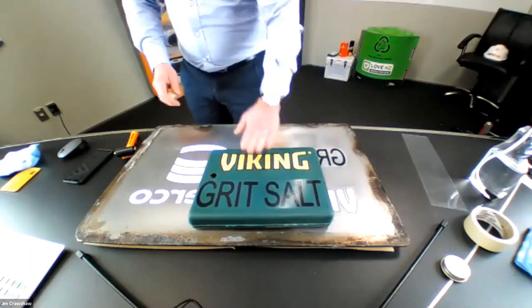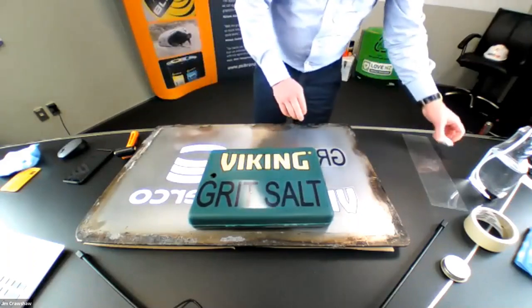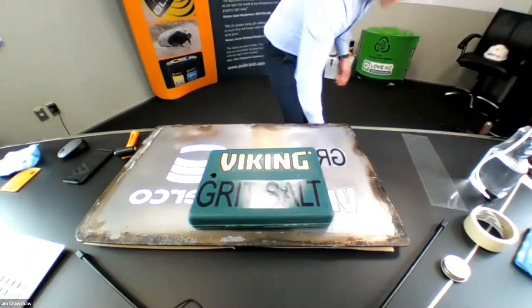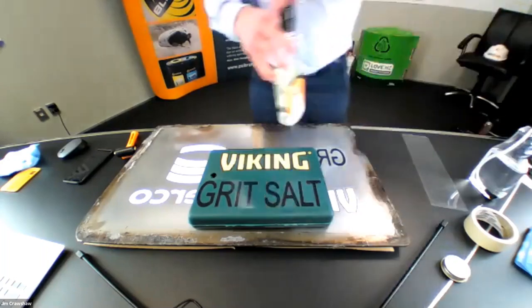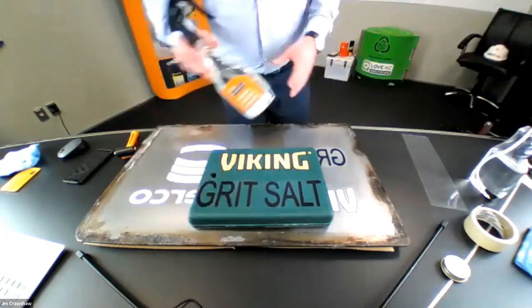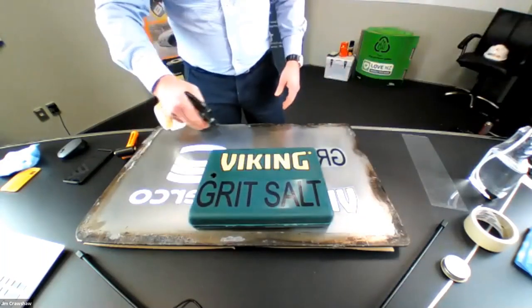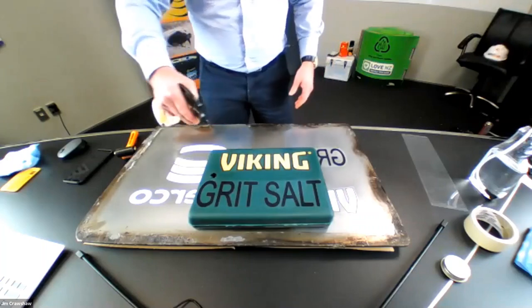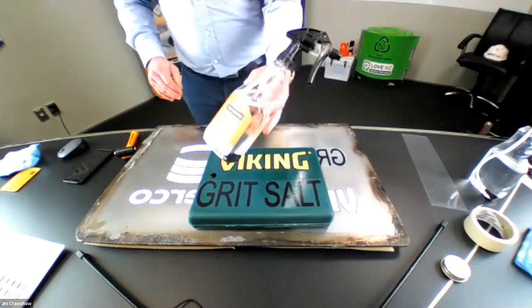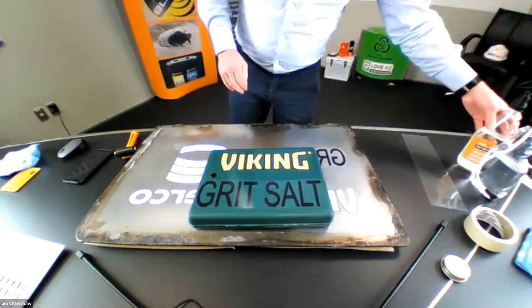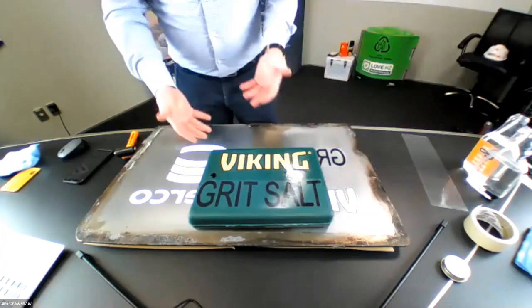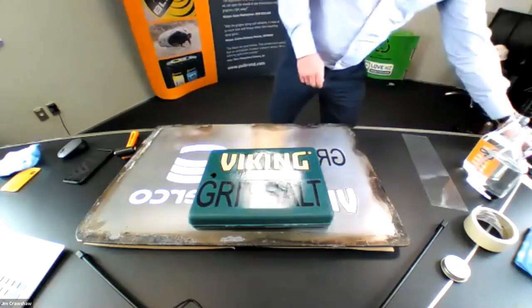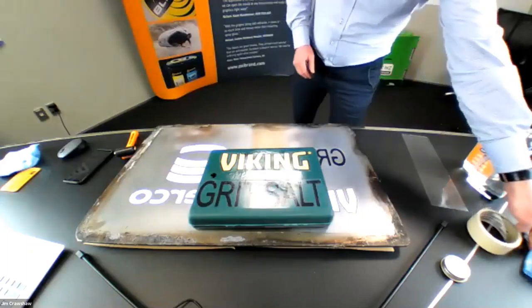So with the Viking one, we've got the standard adhesive. Now we need to clean that off. So what I'm going to use here is our graphic adhesive remover, and just show you how well it works. So I'm just going to give it a quick spray over the surface here. Now spray and scrape, I'm showing the spray and scrape method, which is very fast, very effective. I'm giving it around about 10-20 seconds to let it activate.